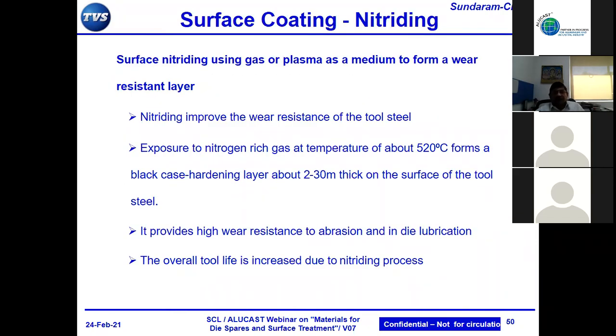So the normal surface coating is nitriding. It's gas plasma nitriding, which normally happens with nitrogen gas and plasma, and which actually creates a few micron thick hardening on the surface of the tool, which reduces the wear and increases the die life.